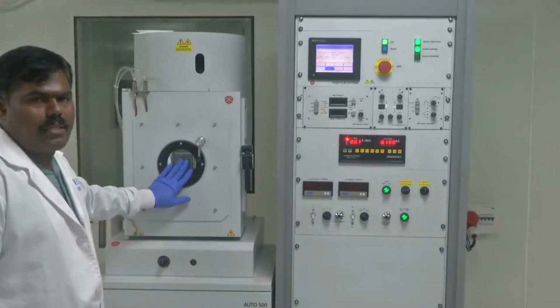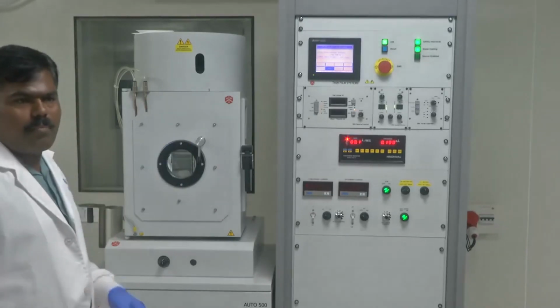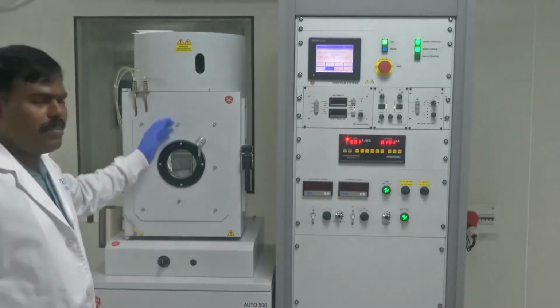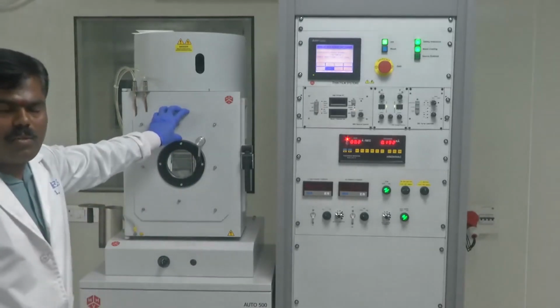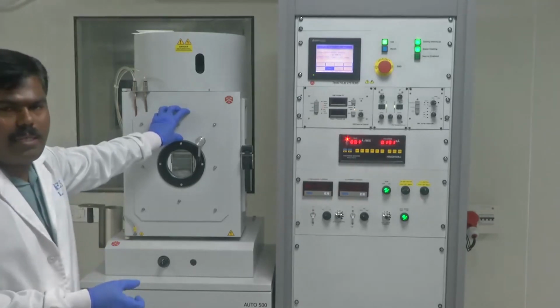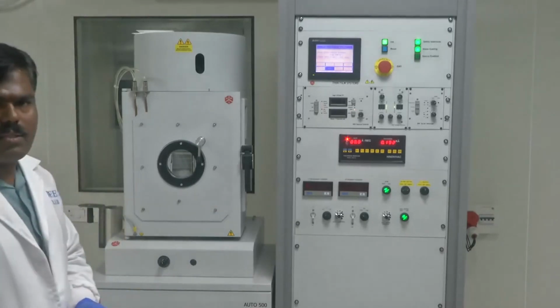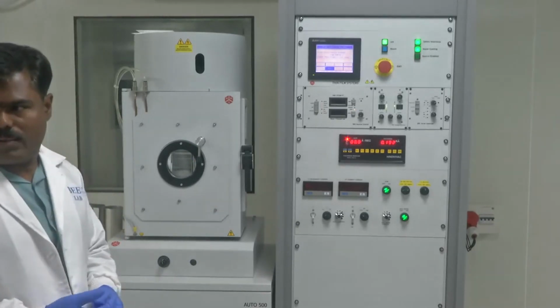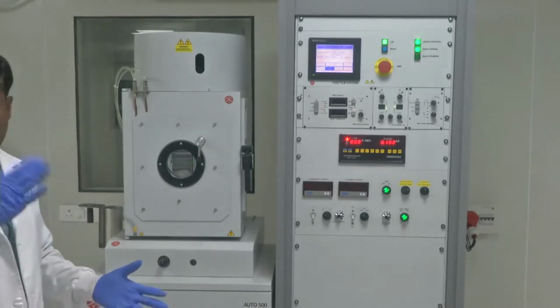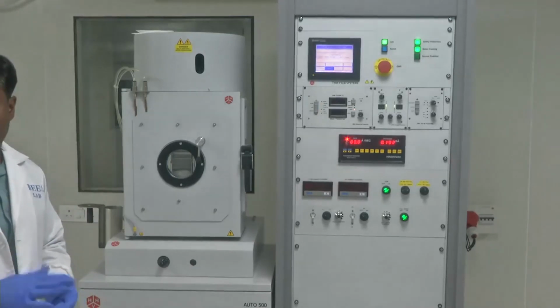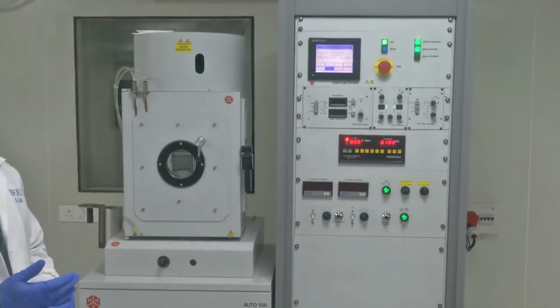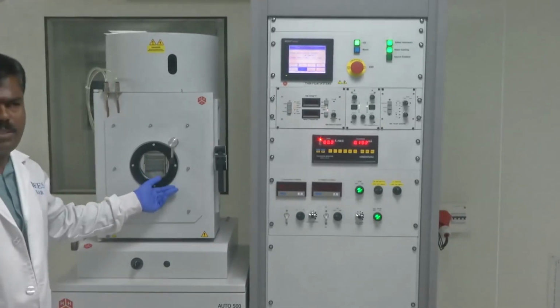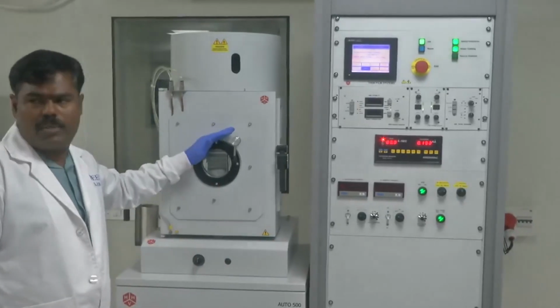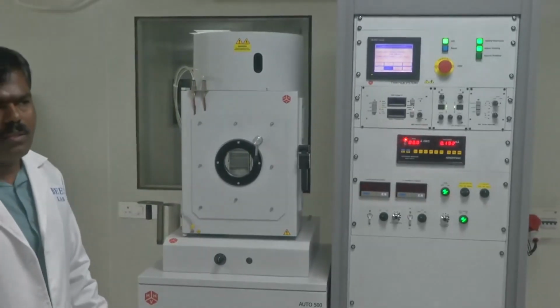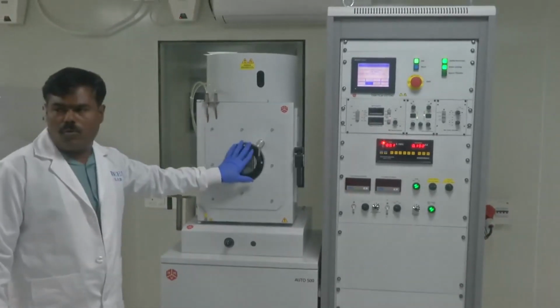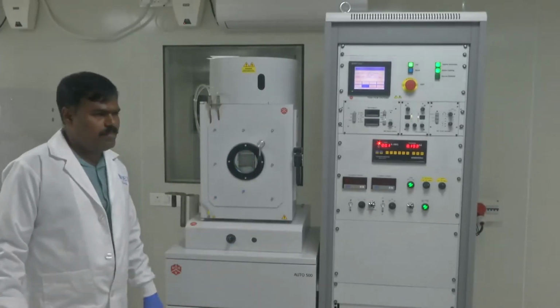Keep the deposited substrate as it is for some 15 to 30 minutes because the chamber is at some temperature. If we unload at this temperature, your coating will be affected, or moisture content will suddenly enter and affect your deposited substrate. So keep it as it is for 15 to 30 minutes. Keep the system in high vacuum cool down condition. Do not vent the chamber, otherwise the film will be spoiled and some contamination will happen.